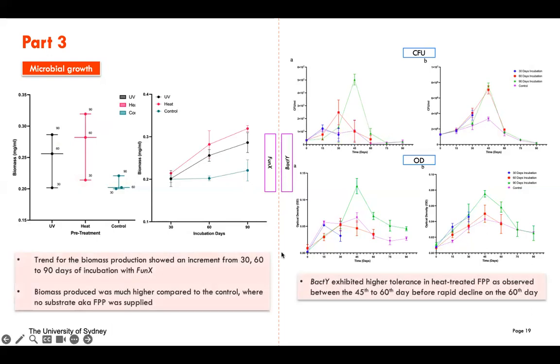But for the bacteria, on the other hand, we can't use biomass to measure its growth, because it is very hard to get bacterial biomass, as they are way tinier than the fungus. So basically, we did a CFU, which is called a colony forming unit, and optical density, where we use a UV spectrophotometer to measure the turbidity of the media. The more turbid the media, the more bacteria present in the media.